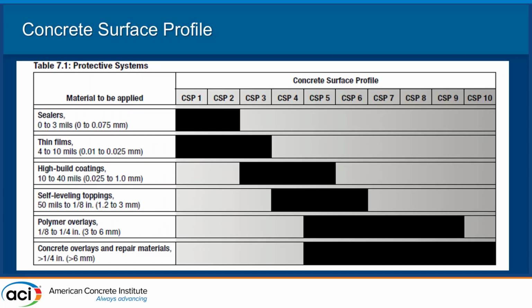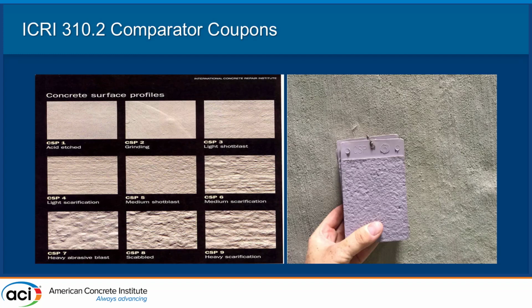You don't want to have a very aggressive profile and then have a thin coating that doesn't cover that profile, because now you actually cause more problems. But as we go all the way down, if we're doing up to a 1/4 inch overlays where you have a very severe environment with a very robust coating with a very thick, heavy system on there, then we can go all the way up to a CSP 10, which if we look here is not something you'd want to walk on barefooted, because it's a very aggressive profile and it's got a whole lot of anchor profile for that coating to adhere to.